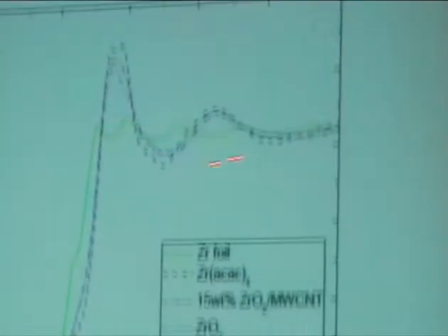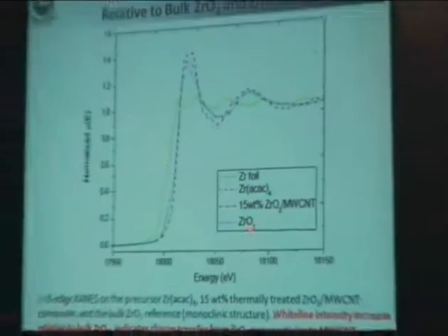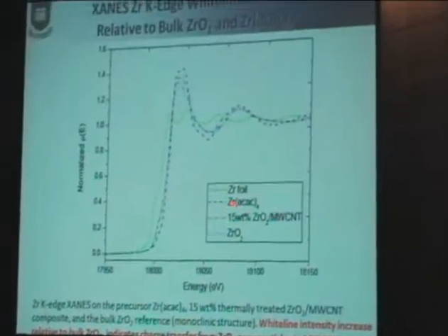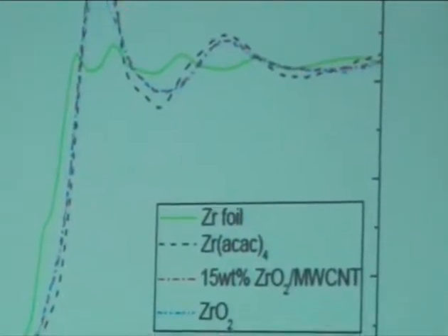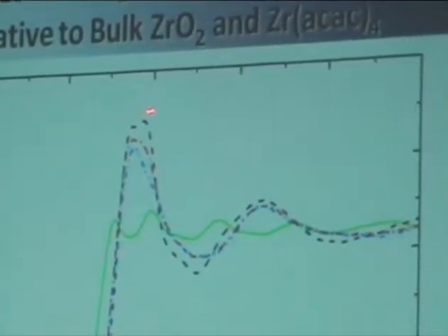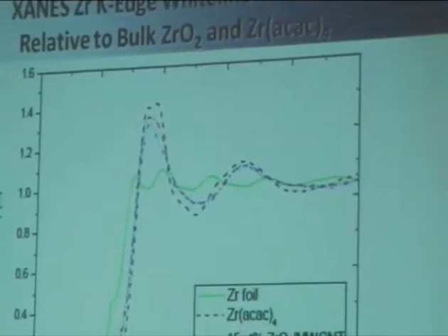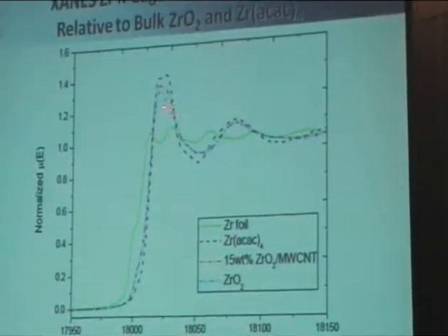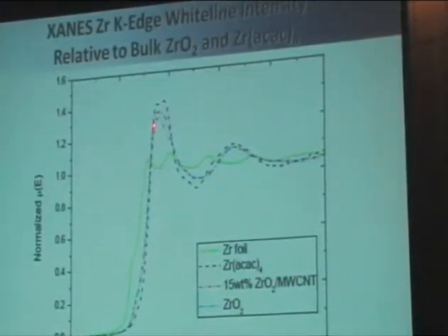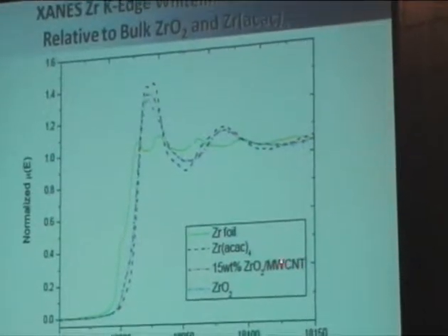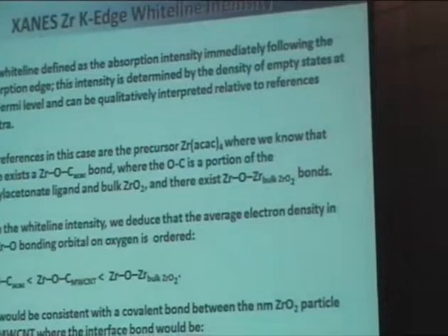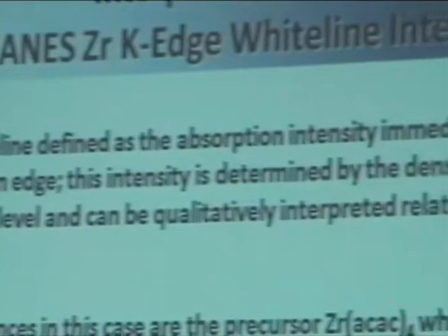So here is the XANES of the K edge of zirconium, and there are several references here. The foil, which is not very useful. The other two are the precursor, the zirconium acetylacetonate, which has the highest white line intensity, and the zirconium dioxide, which has got the lowest of the oxides, and then in between them is our actual catalyst. So how do we interpret the change in intensity of the white line? I'm doing this in detail.